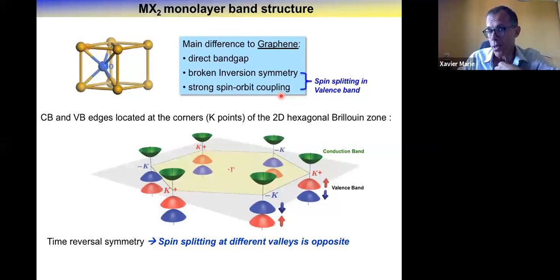So you will have a rather strong effect of spin orbit coupling, which will play a very important role. And the interplay between this broken inversion symmetry and the strong spin orbit coupling will have a strong impact on the band structure. So again, here is a simplified picture of the 2D hexagonal Brillouin zone, where gamma is here at the center, and we have here the conduction band and the valence band at the K valley, as I said previously.